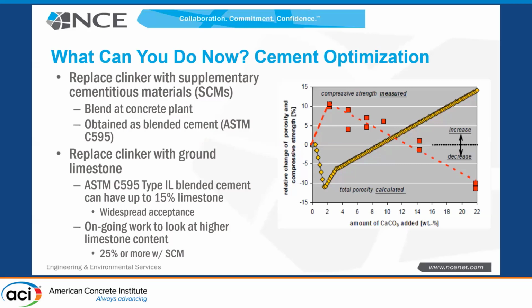And the chemistry here is such, and the particle packing, that with an SCM, with some aluminates, with that ground limestone, you get some benefit that's actually better than the SCM would do without the limestone. So there's a lot of ongoing work right now. People are looking at even higher contents, up to 25%, not for paving. I wouldn't recommend that, but if I'm doing a masonry block or something of that type, it might be perfectly acceptable.